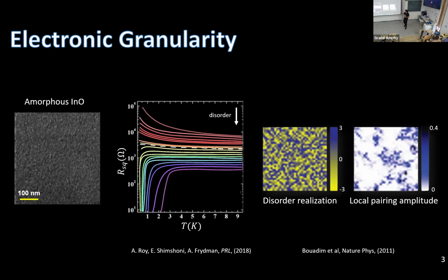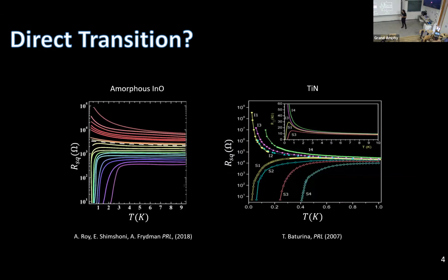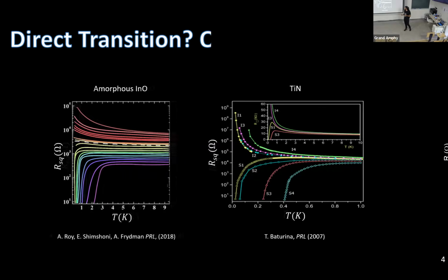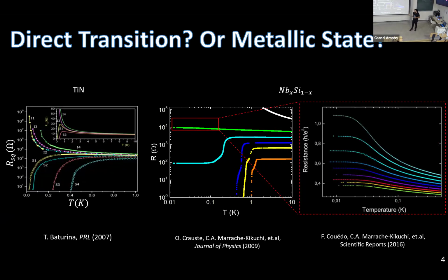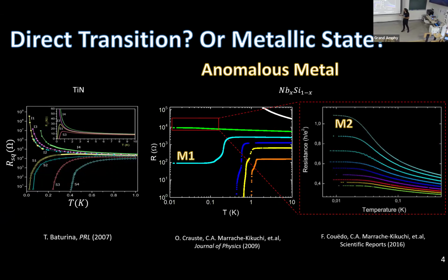Nevertheless, even though this quantum phenomenon was examined a lot over the past years, there are some open questions. One of them is something that we discussed before. Is it a direct transition from superconductivity to an insulating behavior, as we see in amorphous indium oxide, or maybe even a bit more clearly in titanium nitride, where we see only those two phases? Or do we have this anomalous metallic state, which we will call M1 and M2, where M1 is the anomalous metallic state where we see a drop at the beginning and then saturation in the resistance, and M2 where we see at first an increase in the resistance but then saturation, and we see this in niobium silicon and many other systems.